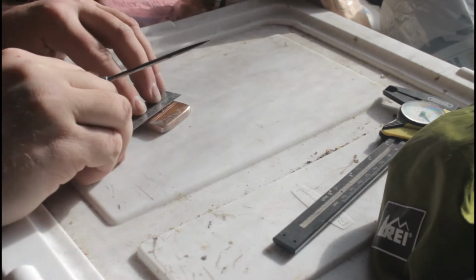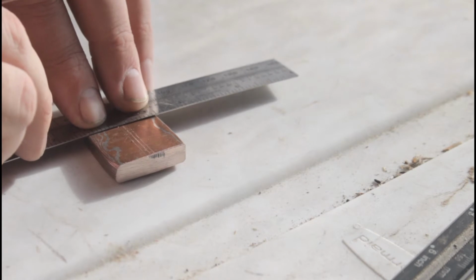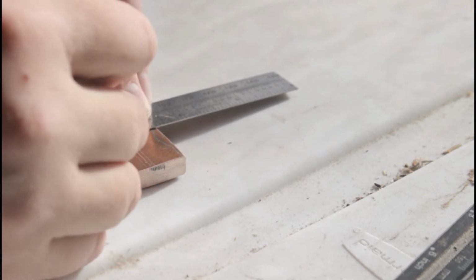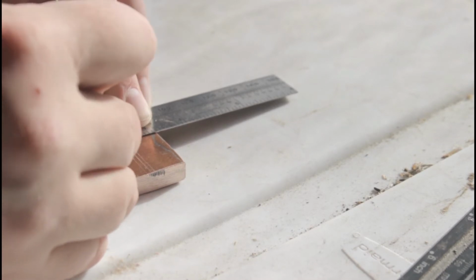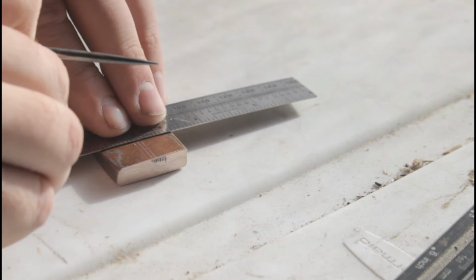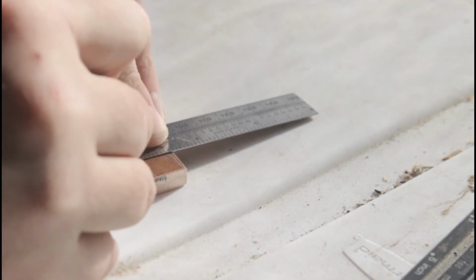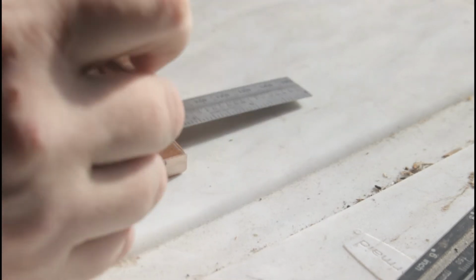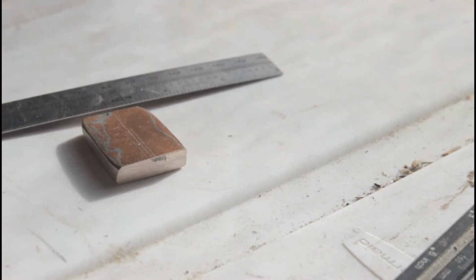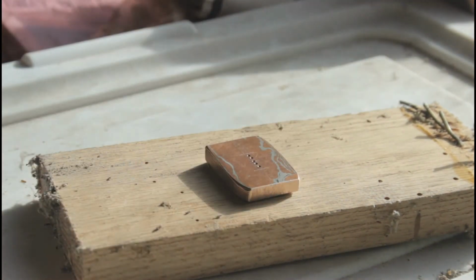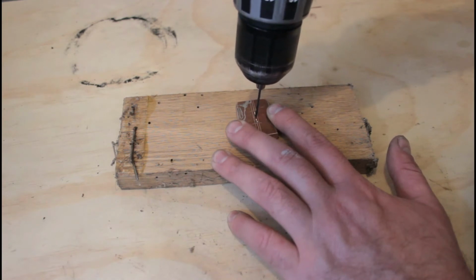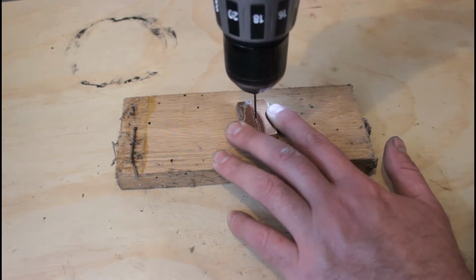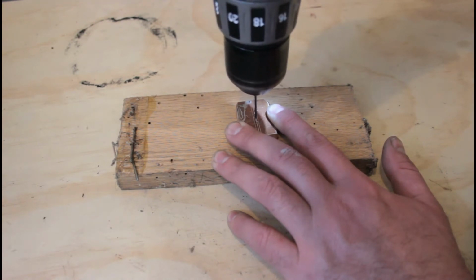Here I'm scribing my layout for where my knife tang is going to go. This turned out to be a mistake. I should not have etched the lines in with a hard scribe. In doing so, I actually cut all the way through the top layer of mokume, which is really, really thin. I mean, it's like 1/1000ths, maybe 2. And because I cut a line through it like this, it wanted to delaminate and start to flake off at the line. So keep that in mind if you're working with this material. Now, I can't speak for other types of mokume gane made in other fashions, but at least for the one that you make out of smashed quarters, just be aware that this material is actually very fragile, despite how it may appear.